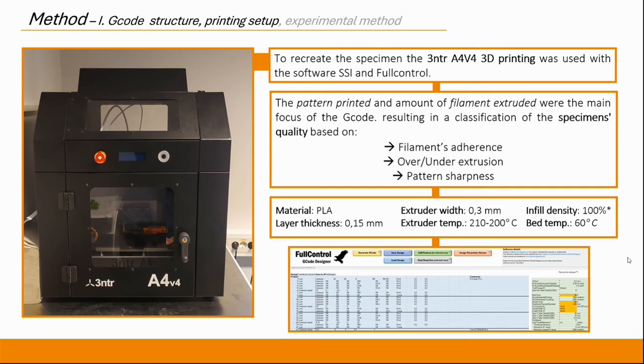The design and G-code writing were performed using full control and SSI software. The layer thickness for PLA is set to 0.15 millimeters, and the specimen was printed using a nozzle with a 0.3 millimeters diameter. We can set an infill density of 100% in the SSI software, but it doesn't take the printer's characteristics into account. This issue will be covered in the printing results section. The extruder temperature ranges from 210 degrees for the rough to 200 degrees for the specimen. The bed temperature is maintained at 60 degrees.